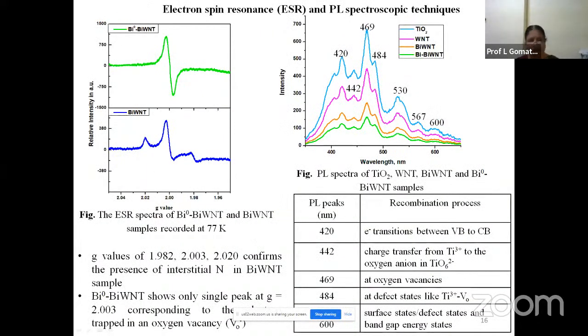So we have taken an ESR spectrum for these samples, and the ESR spectra were recorded at 77 Kelvin, and the BiWNT sample shows 3 peaks corresponding to g values of 1.982, 2.003 and 2.020, confirming the presence of nitrogen in the interstitial site, which is precisely paramagnetic nitrogen oxide. Further, the peak at 2.003 can be attributed to the singly ionized oxygen vacancy. The 2 weak satellite peaks at 2.020 and 1.98 can be assigned to the perturbation peaks corresponding to ionized oxygen vacancy adjacent to nitrogen. And Bi0 BiWNT shows only a single peak of g value 2.003 corresponding to oxygen vacancy, and it is referred to as F centers.